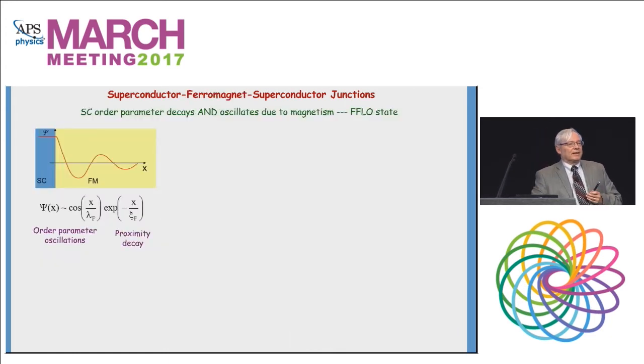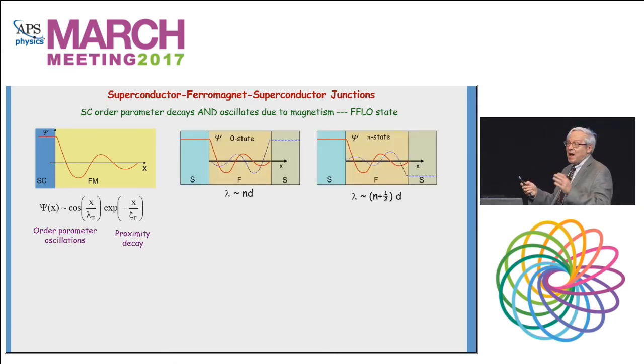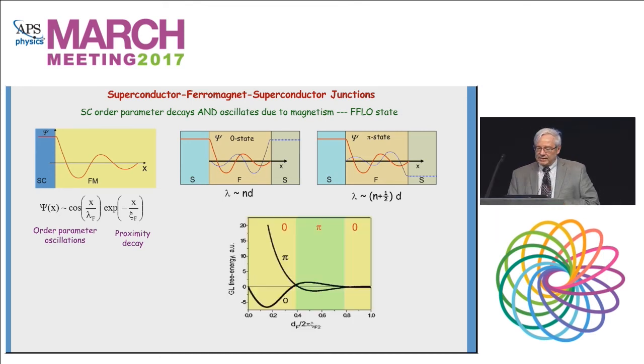What I've been mainly interested in this space is the superconductor-ferromagnet-superconductor junction. When you have an interface between a superconductor and a ferromagnet, the order parameter not only decays, it oscillates due to the exchange interaction. And so if you can make essentially a particle in a box, a Josephson junction, where you have decay from both sides, you can have the possibility of a 0 state, where the lowest energy state is a phase change of 0, or you can have a state where the lowest energy is a phase change of pi. And as a function of the thickness of the barrier, you can move between those two and get this 0-pi transition.